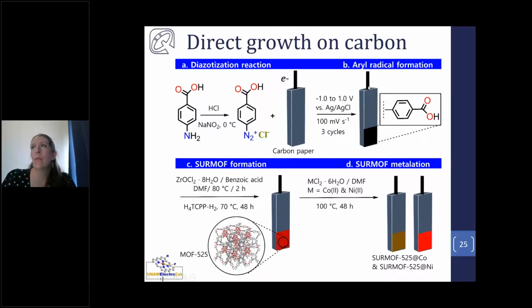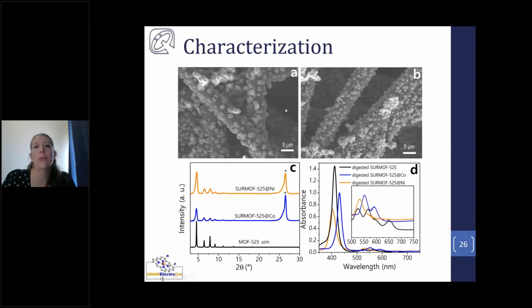What we ended up finding as the most efficient method to prepare these MOF-based electrodes was to first modify the carbon paper. So we functionalize it to have a carboxylic group that helps as a starting point for growing our MOF. So we grow the MOF directly on the carbon paper, and when we have it grown, we can metallate it with cobalt and nickel. The characterization of the MOF shows that we have grown some MOF particles on the carbon nanofibers that we show here. So we still have this porous carbon paper covered by the MOF. So this could be useful in different applications for electrochemistry where we have a porous electrode.